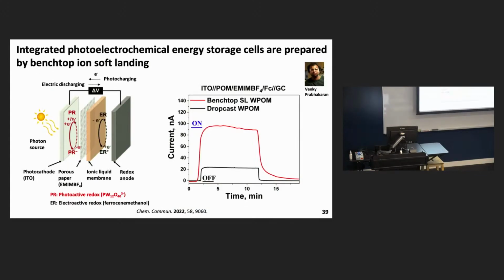Another area that we worked on recently was using the same technique and clusters to try to prepare a device that would basically harvest and store energy in the same device. So we called it a photoelectrochemical energy storage cell, but it looks something like this, where you have an indium tin oxide surface. We deposited polyoxometalates onto that using Andre's device. And then in between that, we had an ionic liquid layer and then a redox anode. And when you shine sunlight on this, a broad spectrum light, it does in fact generate current, and that's what's shown on the right-hand side here.